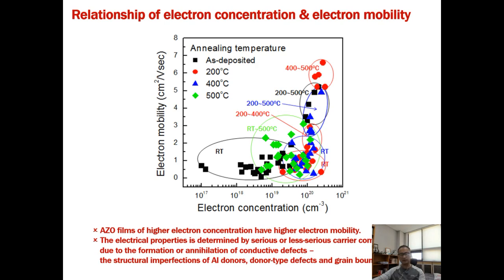We can say that the electrical properties in the AZO films are determined by serious or less serious carrier compensation due to the formation or annihilation of a conductive defect, such as structural imperfection of aluminum donor, or donor-type defect and grain boundaries.